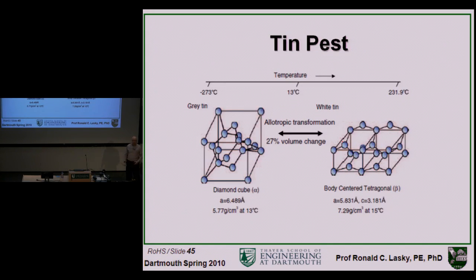My mind is going blank. The tin and antimony, pewter. Pewter has a lot of tin in it. It's normally body-centered tetragonal, has a density of about 7.3 grams per cubic centimeter, and this is what it is at above 13 degrees C. But an amazing thing happens at below 13 degrees, or I should say can happen at below 13 degrees C, and that is it takes an allotropic transformation, and it goes to a diamond cubic phase, the alpha phase, and its density drops.